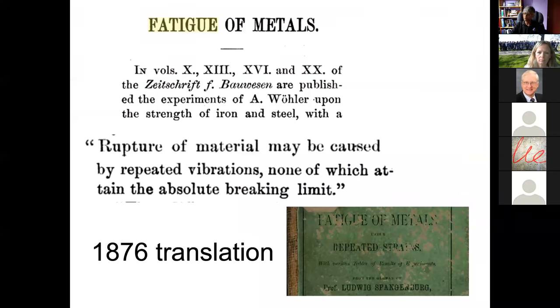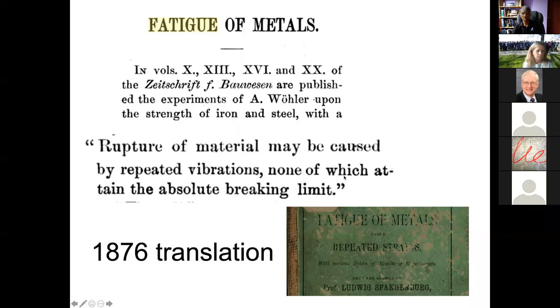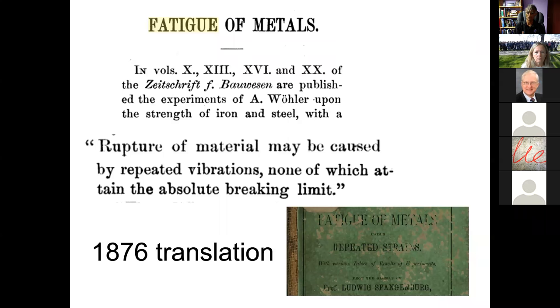Then you have the classic work of Wöhler, who designed experiments to measure fatigue strength in a rotating bending sample. His 1876 definition of fatigue is very precise: it's the rupture of material which may be caused by repeated vibrations, none of which attain the absolute breaking limit. The macroscopic yield strength may be much greater than the stress at which material fails by fatigue, which is why fatigue tends to be a very dangerous phenomenon. I heard that something like over 90% of failures of metallic materials is due to fatigue — it is perhaps the most important failure mechanism.